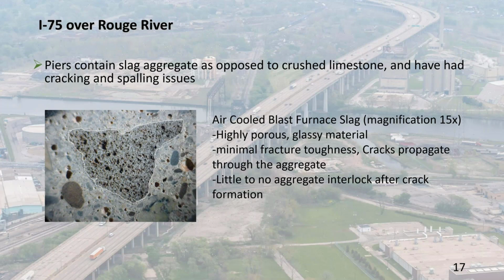So if you do any patch repairs with slag aggregate, you want to first carefully make sure that you define your removal areas, because if you take a hammer and chip away, you'll find you won't be stopping. So you have to essentially carefully lay out the repair area and stay within the confines of that area. And you're also going to need a way to maintain or hold that patch in place throughout the life of the structure.